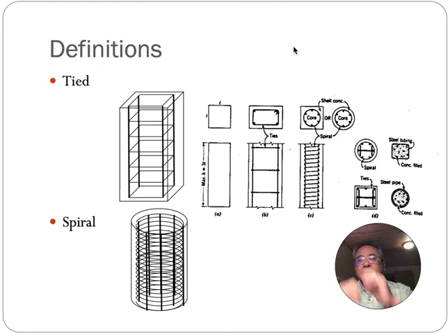And with the spacing from the Illinois equations, they were far enough apart that those bars could buckle. And so the current spacing recommendations for columns, which we'll get into later, take that into account. But unfortunately, I'm oversimplifying it, we didn't really realize this till the mid 70s.